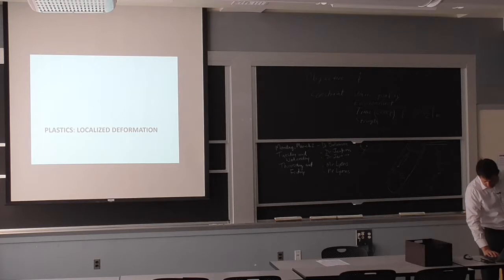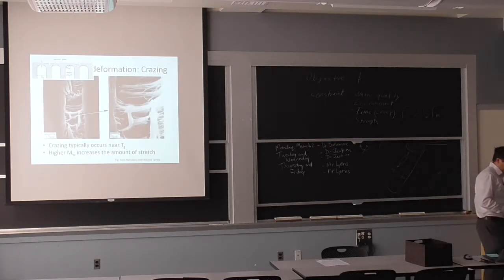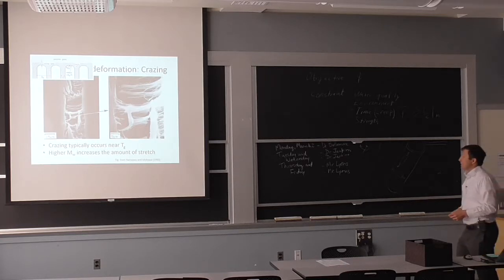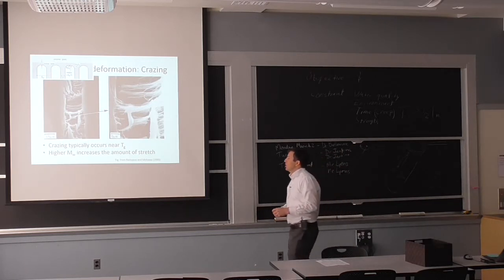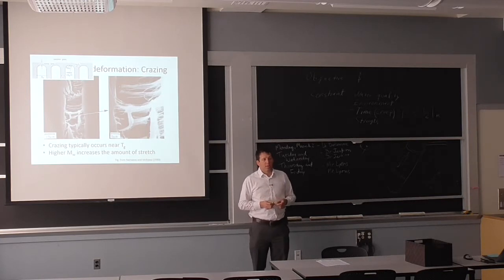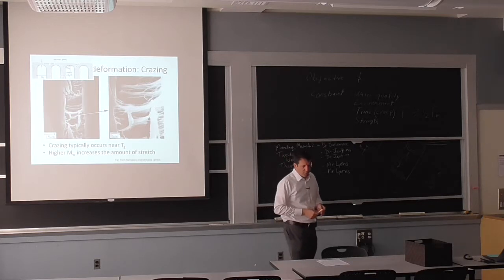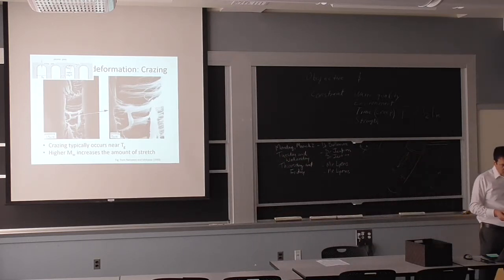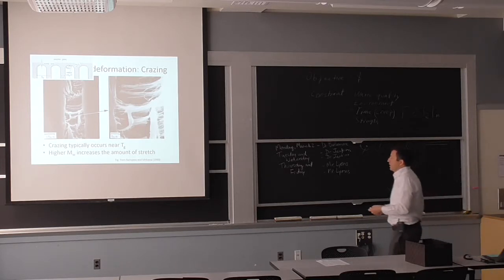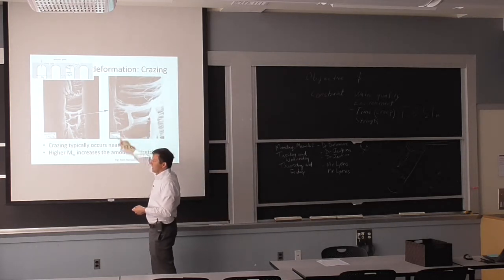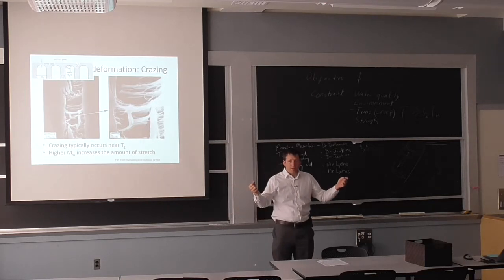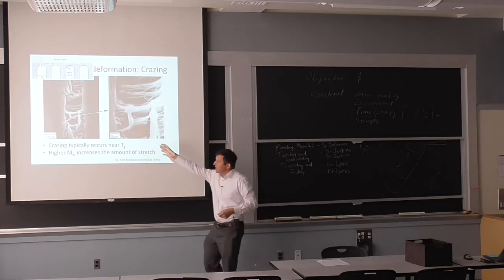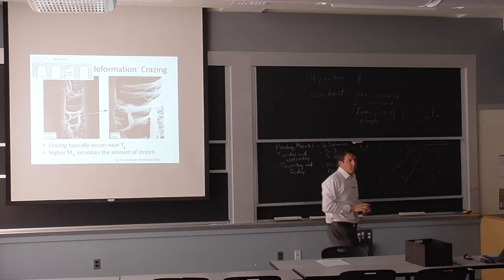So let's go into more detail about how it will potentially break, crack. The first one here is what we called at the beginning the stress whitening. So you create microvoids, and these, by the way, are not all that different from the dimples that we discussed on Monday for metals, this idea that you create these microvoids when you're deforming. What is really unique here is just like you form the nylon cords by this drawing process and make them much stronger, the fibrils here in the crazes do the same thing. They're still connected on each side, and they still hold the crack-like feature together, the crazes together. So this is still carrying load, as opposed to being a crack like you'll have at that point on a metal.